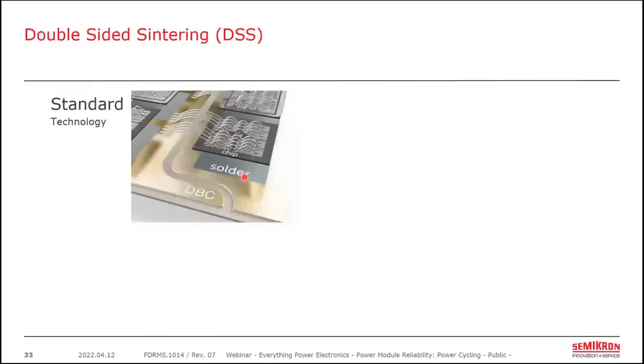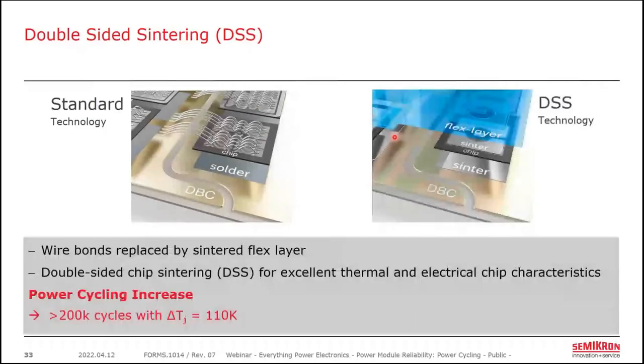And in what we call our double-sided sintering process, we replace not only the chip solder layer as described before, but we also replace the top side connections to the chip. Instead of bond wires, what we use is a flexible layer with conductors in it, similar to maybe a flexible PCB, if you've seen that before. This allows for a much larger contact area on the top of the chip to be sintered. In addition, it also reduces the loop area in the conduction path in the module, and hence the stray inductance in the module.